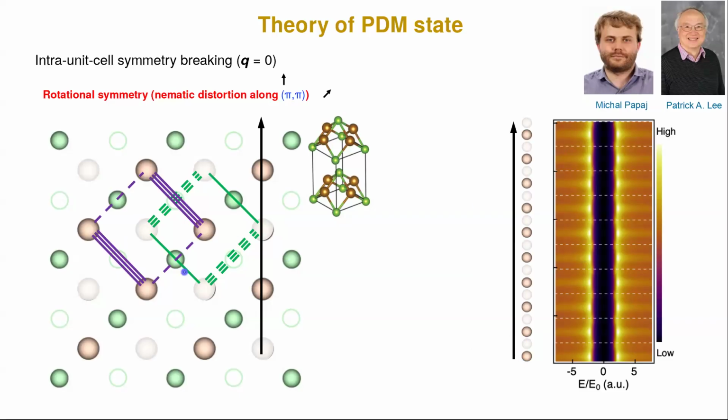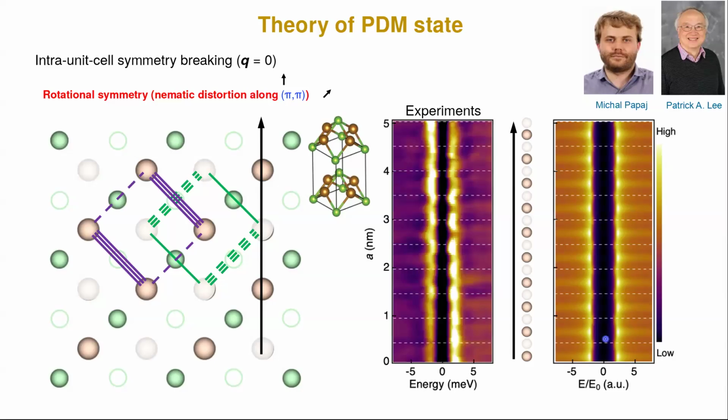So in this particular configuration, if you assume that there is a different coupling in this direction than this direction between the iron atoms into two sublattices, you would get the periodicity of the superconducting gap, which is exactly what we found in our experiment.